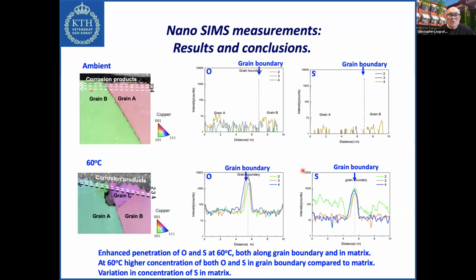Here we can see more about the distribution of oxygen and sulfur. These are the results for ambient temperature. These are the results for 60 degrees. At ambient temperature, the corrosion products are up here. This is the one grain, this is the other grain, the grain boundary in between. And for ambient, you can see that we have done line scans here at different distances from the surface, from the corrosion products. And at ambient temperature, there is basically just background levels. There is nothing pronounced in the grains, and there is nothing pronounced at the grain boundary.